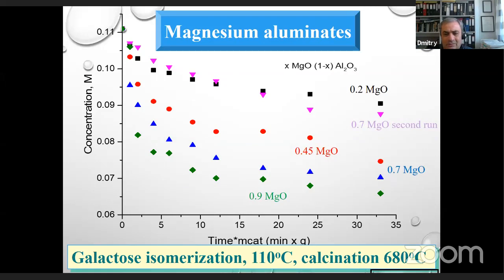This is a little bit complicated slide, presenting the concentration curves. What I want to show here are the concentration profiles for different types of materials with different amounts of magnesia, 0.9, we see here 0.7, 0.45, 0.2. So apparently, as we can see, the higher the amount of magnesia, the more active is the catalyst. Unfortunately, the recycling of the catalyst was not very successful. In the second run, as you can see here, the 0.7 MgO catalyst was less efficient than in the first run. But still, we see some clear trends.